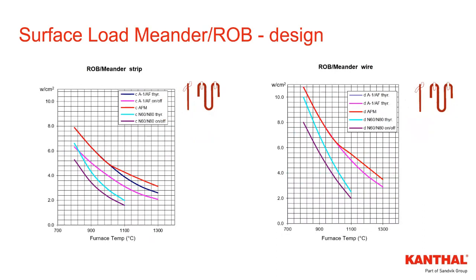Another example I have here is for ROB or meander type heating elements. So ROB stands for rod over bend, so it's essentially just a sine wave or a loop of material. The recommended loading for the design can vary depending on if it's using round wire or strip material. And again, differences between nickel chrome and iron chrome aluminum. And also you'll note on here that it also shows differences on how the elements are controlled. So it all has to do with the control system, whether it's on-off, so it's cycling through a SCR that might be burst fired or zero cross type, or also a type of control where it's using more of a softer phase angle fired SCR.